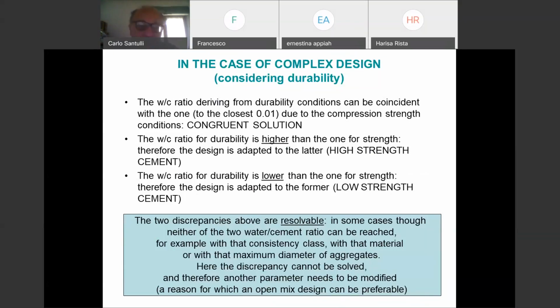So I have a low strength cement. In this case, it is resolvable because I take two indications, durability and strength, and I adapt to the lower water to cement ratio, provided it is workable. It needs to be sufficiently high for the cement to be workable, and then I adapt to the one that puts me less into trouble, because basically if I have a low strength cement, I have to adapt by increasing the strength of cement, and therefore I have to reduce the water to cement ratio. In this case, I always try to reduce the water to cement ratio, provided that workability is ensured.